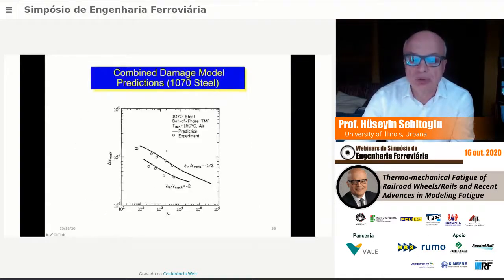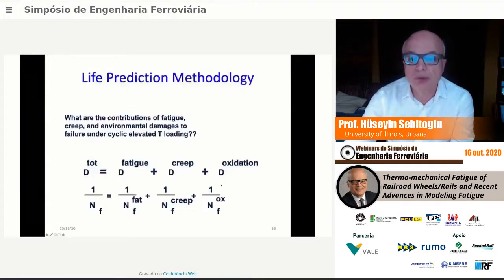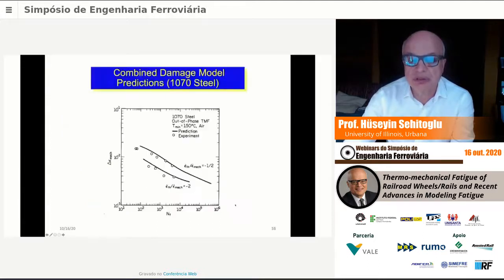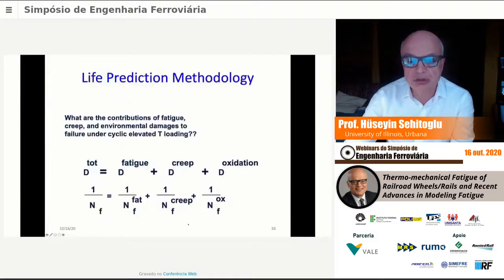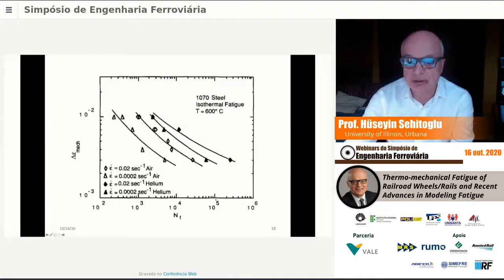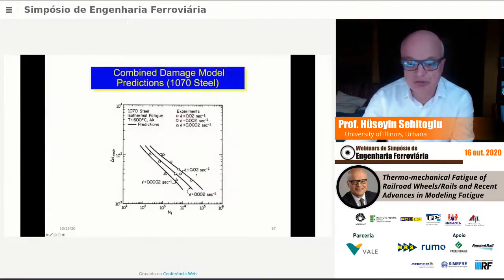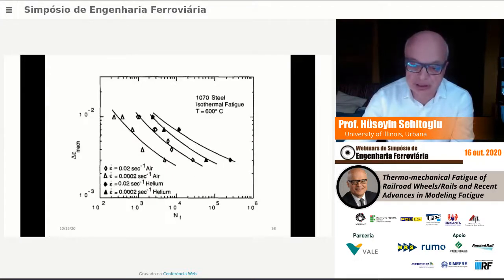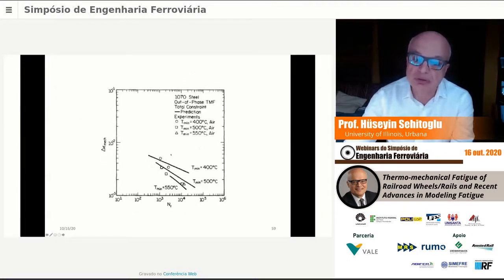We also conducted, of course, tests in an inert environment. By running these inert environment tests, we basically don't have the oxidation damage term. Then we can configure the fatigue and creep from that. And then from the in-phase and out-of-phase differences, we can assess the amount of creep damage that's going on. So we systematically evaluated those terms based on these experiments.